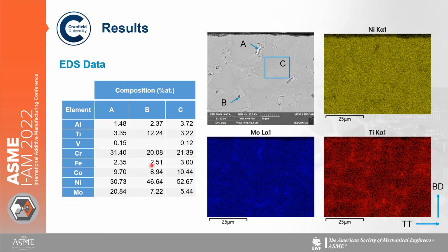And then if we look at these darker coloured phases, which is spectrum B on the table, and which is this one here, you can see it's rich in titanium, which is confirmed by the composition, where we see quite a big increase in the percentage of titanium versus the base composition.